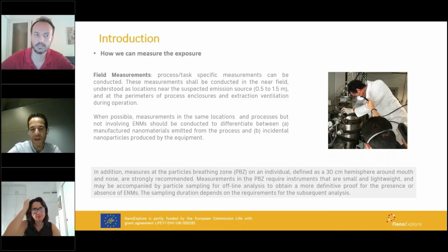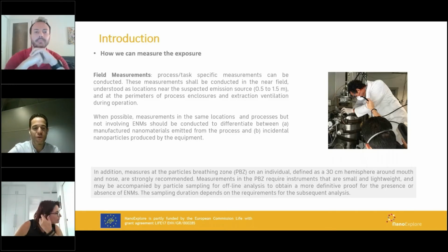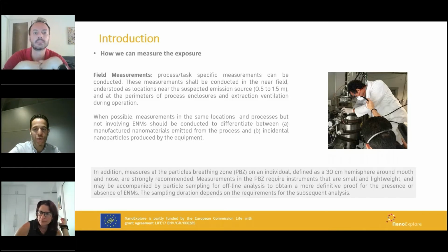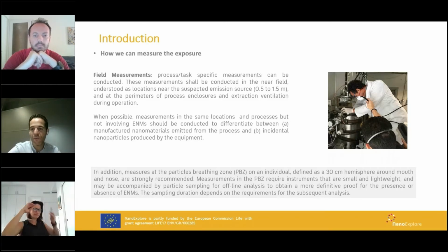This kind of instrumentation only tells you about the potential concentration, but not the chemistry of the material. So normally we prefer to combine in this tier 2 analysis the particle number concentration, but also using filtration sampling in pumps, for example, just to go with this sampling to the microscopy, and then analyze using SEM or TEM the chemistry of the materials.